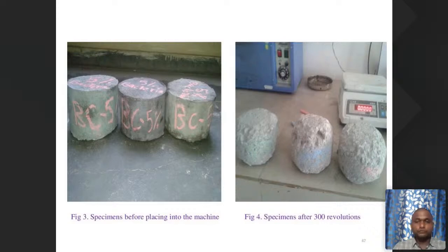If you observe the pictorial view in the images, the first image is the specimen at 24 hours, that means after casting. Then after 28 days of curing, once kept in the machine, the specimens rub against each other. If your concrete quality is not good, they will collide with each other and collapse. That means your concrete is not good. We perform the abrasion resistance test especially for concrete roads, that is rigid pavements. If you don't perform this Cantabro loss test on rigid pavements, it's very difficult.